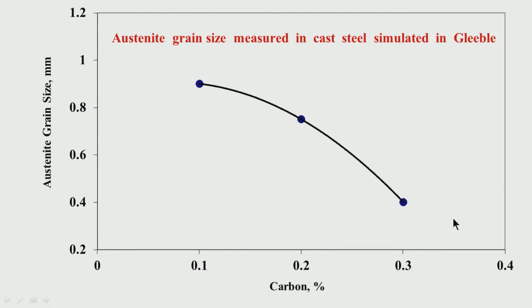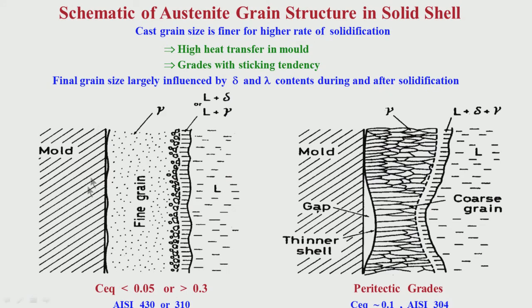This, of course, is the cast grain size, and for around 0.3% carbon it is decreasing as you increase the carbon. As I have told you, when you say 0.3% carbon, you are coming to a situation where the sticking tendency is quite high, and 0.1% carbon is a depression tendency. Depression means there is a gap formation on the surface, a hot spot formation on the surface, and heat transfer is low because of this, and we have relatively coarse cast grains of austenite. For sticking tendency, if you have very low or very high carbon, say 0.3% carbon, it is a sticking characteristic.